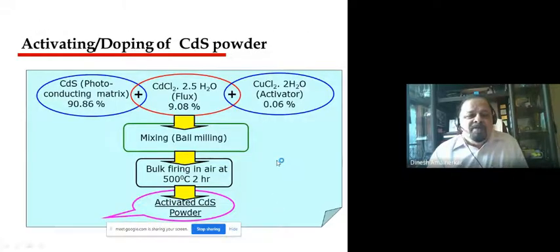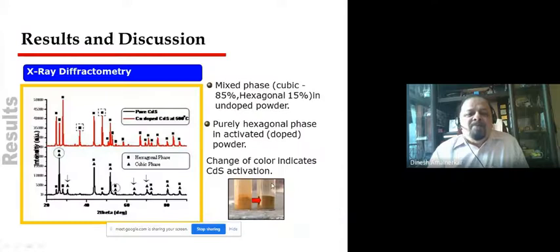How do we do that? We take cadmium sulfide, which is a typical photoconducting matrix, very high purity. Add cadmium chloride in that, also add copper chloride in that, and then we subject it to ball milling and carry out bulk firing in air at 500 degrees centigrade for 2 hours, as a result of which we get activated cadmium sulfide. How do we know we have got activated cadmium sulfide?